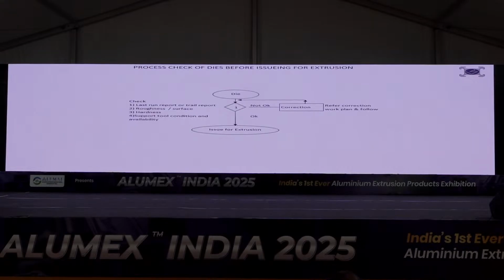That is why it is a must to see. This is a very simple and very small matrix. First, you have to identify your process. If you have a die, before issue, please check these, at least these potential areas. It can be more also. People are there, but they don't check. They directly go for polishing. If any one of these is not conforming to your quality standard, please do the correction, go back for checking, and issue for extrusion in the die area.